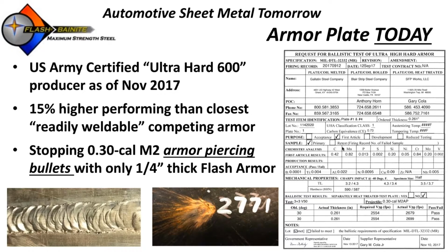What I mean by that is high hard 500 Brinell is what the Army uses a tremendous amount of to weld up their vehicle hulls and other things, be it a guard shack or something else. They do this because ultra hard 600 is very, very difficult, if not impossible, to weld. You have to preheat to 350 degrees, use austenitic stainless steel welding rod, and then post temper at 350 degrees to avoid a brittle weld zone. I don't just mean a weld that looks pretty. I'm talking about embrittlement that you investigate with hardness mapping.